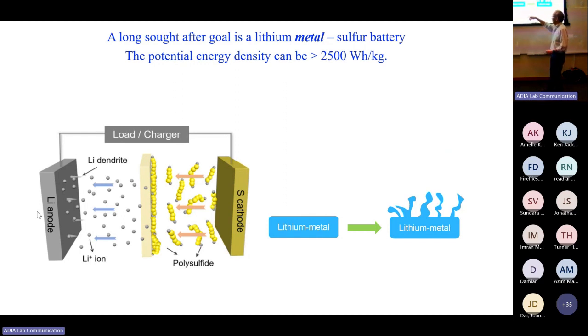And this is an example of a sulfur lithium metal battery. Why this? Because it potentially has the highest energy density of any lithium technology we know about. But if there's a little bump on the surface of the lithium, that is a higher electric field. It induces the lithium to deposit there, and that bump grows into dendrites and it shorts. And so if you can find a way of getting rid of these dendrites, you're home free. There's a bunch of ways people are thinking of doing that. We also are thinking of ways of doing this.